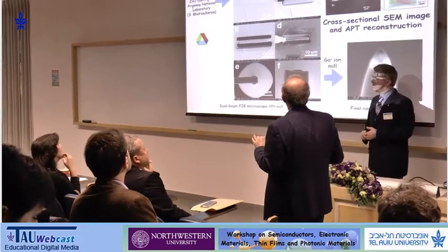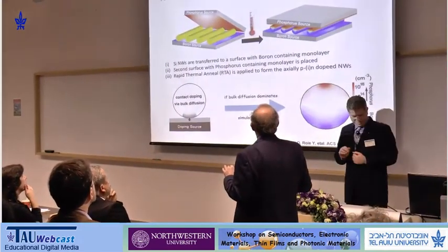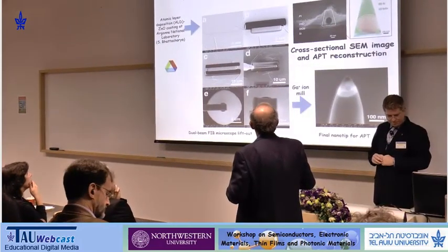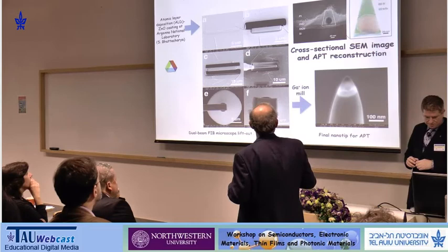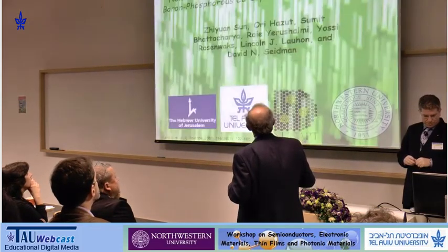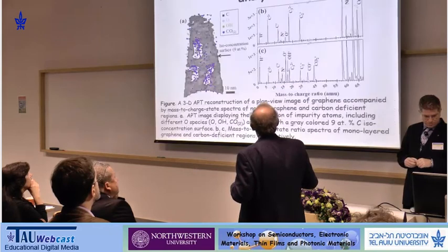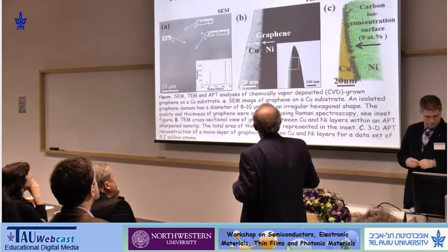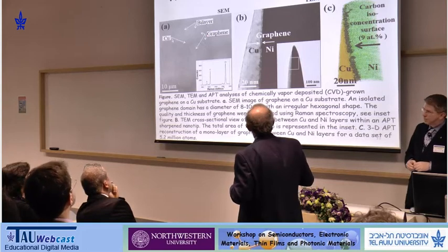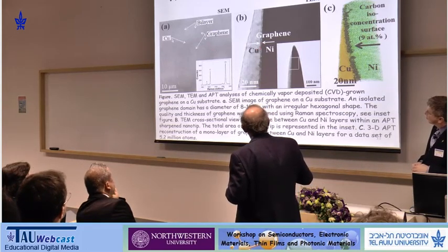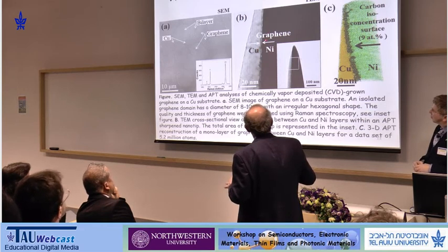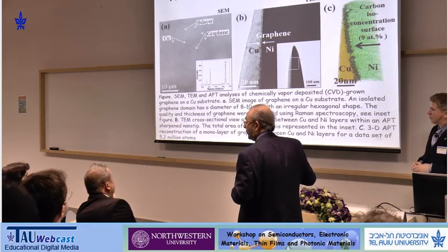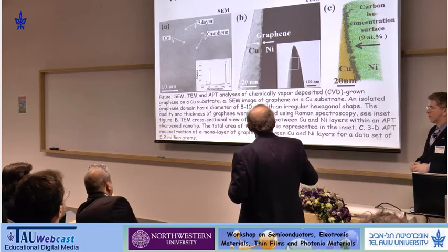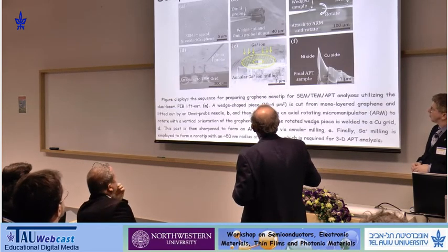Let me go back. This is for the graphene. I have to go all the way back to the graphene. Okay. So here's the graphene layer. This is an SEM picture, and it's grown on copper foil. And then we make a sandwich by depositing nickel on top of this. So you have a sandwich here, and this is the nanotip that we look at. The graphene is sitting here, here's nickel, and here's copper.